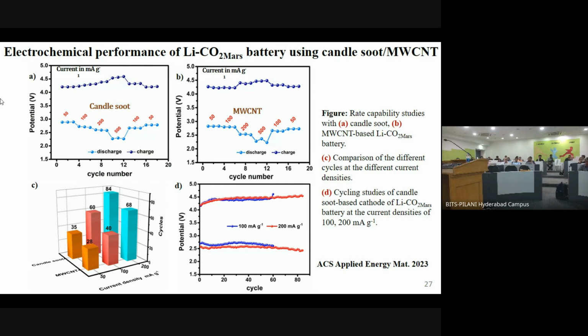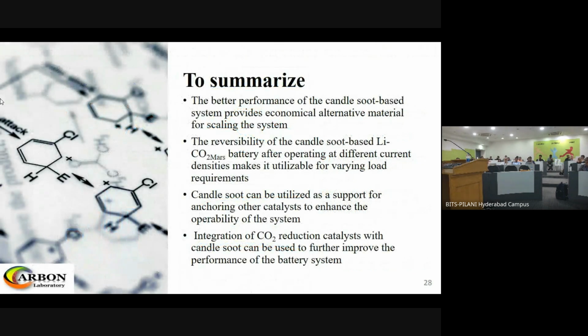Even at a given current density, you can see it goes up to 84 cycles, and this multi-walled CNT fails at a lower number of cycles. So what we have tried to establish is that rather than going for the multi-walled carbon nanotube as a support for the catalyst, we can still use the candle soot more efficiently.